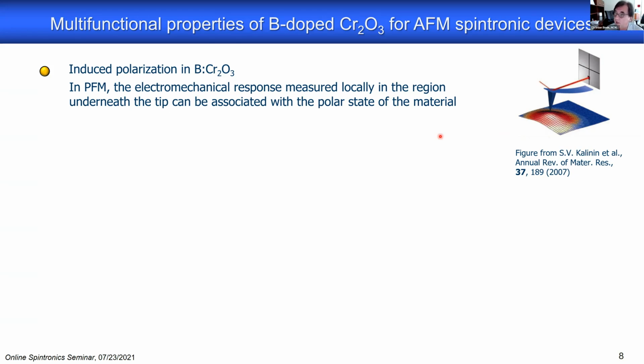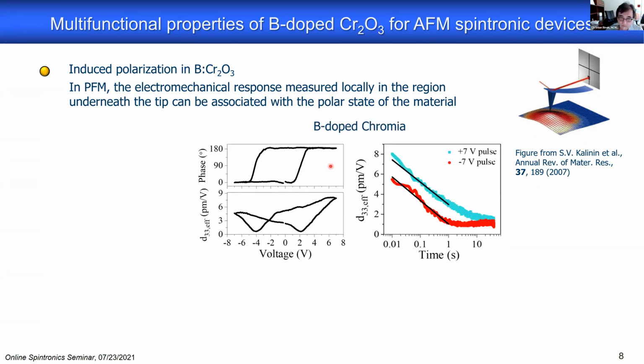And that piezoelectric effect is always there as soon as your system has some polarization. So we can measure local polarization via this piezo force microscopy, via the electromechanical response. And if we do that on boron doped material, we find a rather surprising result if we go through such a hysteresis loop. So you apply a voltage locally to the system. You find this hysteresis in the phase of the signal, which for the experts in piezo force microscopy looks exactly like the signal you would get when you measure a ferroelectric system, a system that has spontaneous ferroelectric order. And similarly, this butterfly-shaped effective piezo response coefficient is indicative of what people would immediately say, oh, that looks like a ferroelectric response.